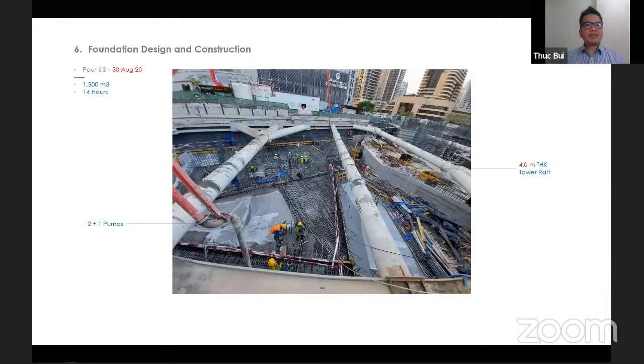Pour 3 was completed on the 30th of August 2020. We put in 1,300 cubic meters of concrete, and it takes 14 hours to complete. So the total volume of concrete for the foundation is 10,800 cubic meters, and total tonnage of rebars is 3,300 tons. So the reinforcement ratio is around 300 kilograms per cubic meter of concrete, including starter bars.